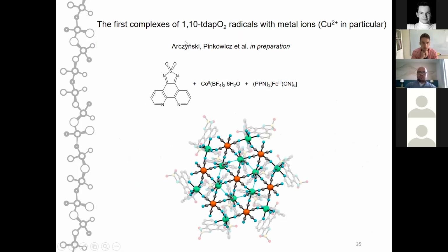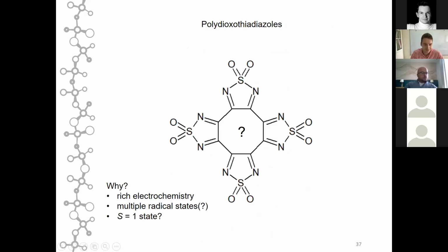So after that, we also tested 3-component compounds. When you combine the dioxothiadiazole ligand with cobalt 2 and hexacyanoferrate, you end up with this beautiful trigonal molecule where we have 19 different metal centers, and it gets even more interesting because the outer 3D metal centers are 6-coordinate, while the internal ones are 5-coordinate. So we already started a project where we rationally introduce 3D metal ions that have a 5-coordinate preference, like copper 2, into these internal positions, and manganese 2 as the metal ion that has a strong 6-coordinate preference on the outside positions.